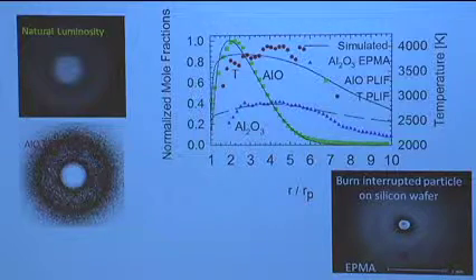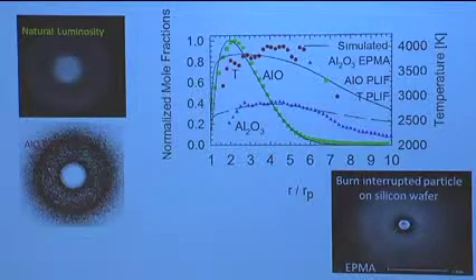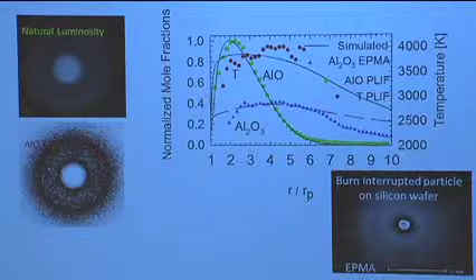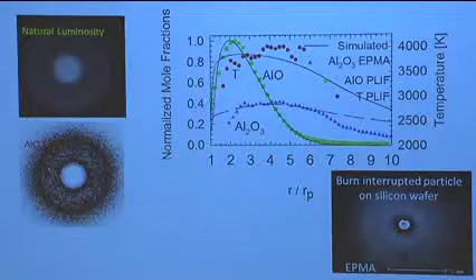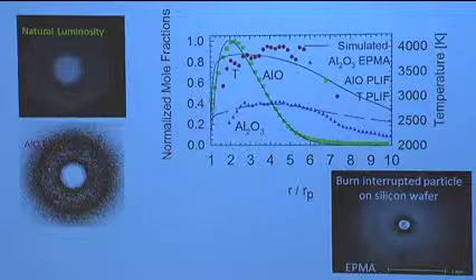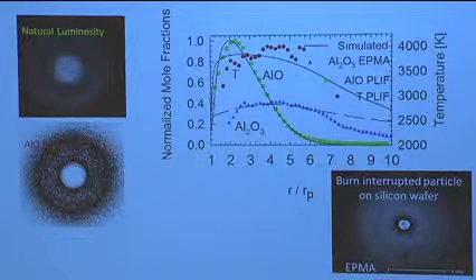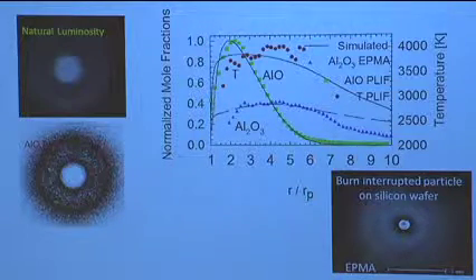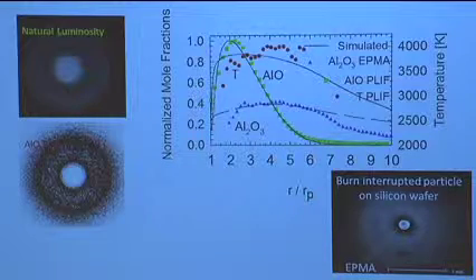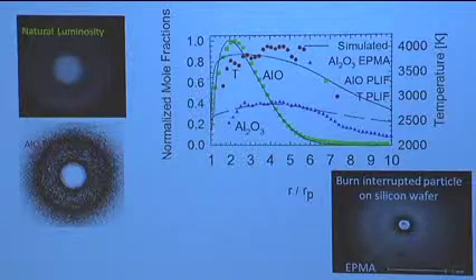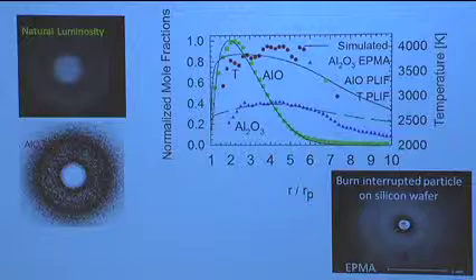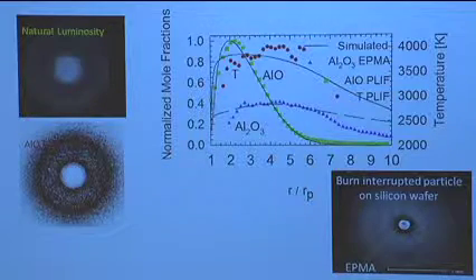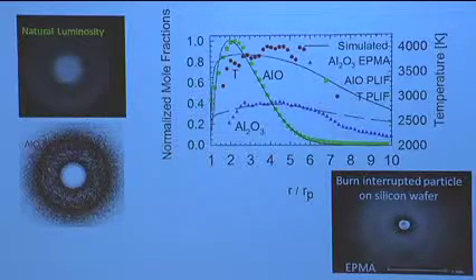And what I show here, this is really the fluorescence image from aluminum monoxide. And you can see here then, this is again for a 200 micron particle, so I'm still dealing in the micron scale. This is a function of non-dimensional radius off the surface. And what you see is that essentially aluminum is being vaporized, it's diffusing outward. As the aluminum leaves the surface here, I start to form the smallest suboxide, which is aluminum monoxide. It peaks, and then it starts getting consumed, and then I start forming my final product.